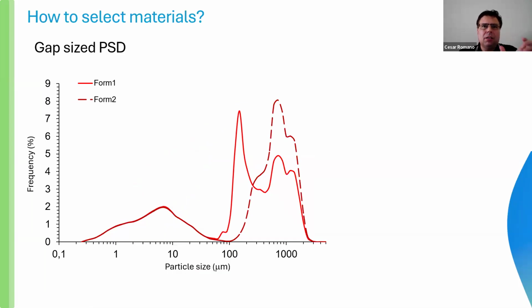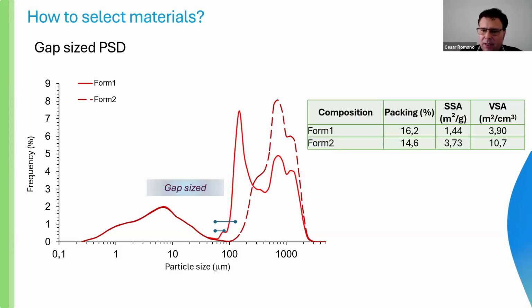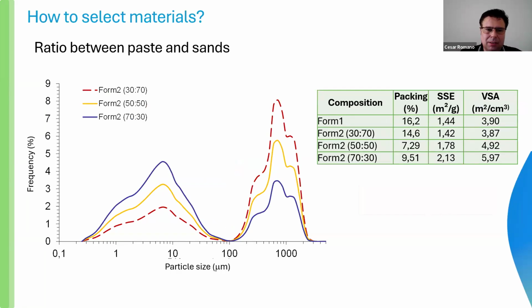And then you can mix the finer development with the sand development, with the coarse development, and then you can choose if your particle size distribution will be prepared with gap size, for example, or will follow a continuous concept. In this composition here, we have 30% of finer particles and 70% of cement and of sand. But we can also change this depending on the target you have for your composition.